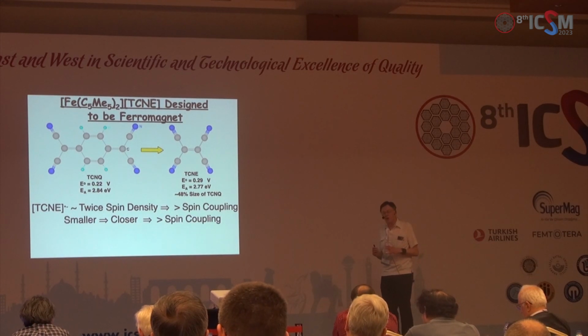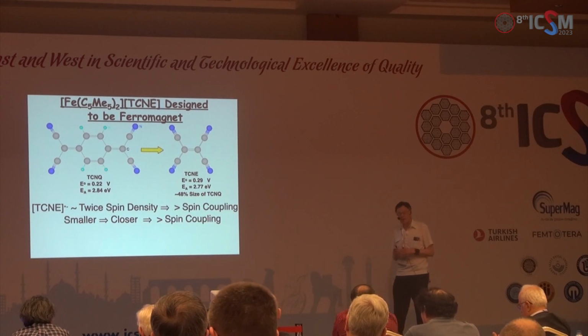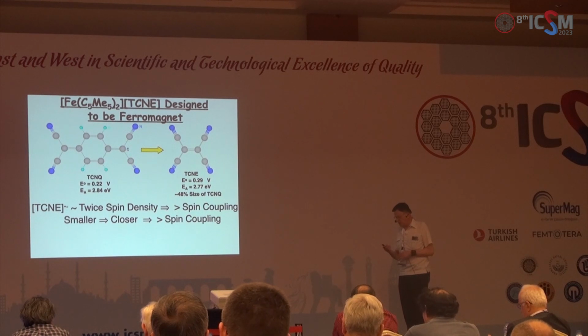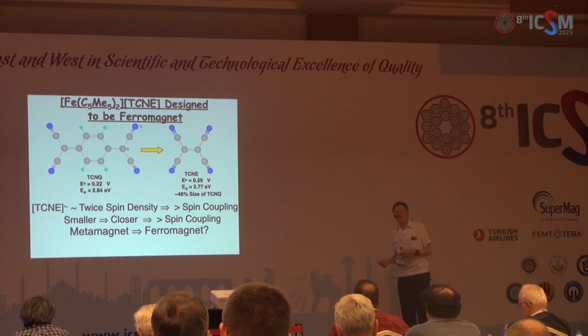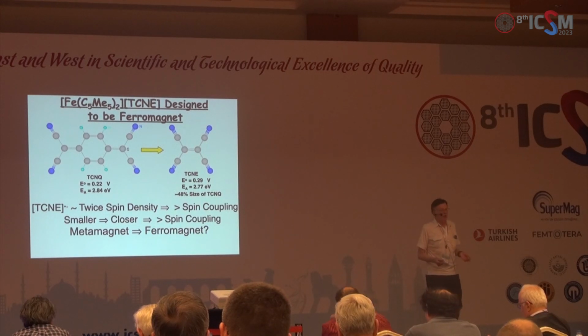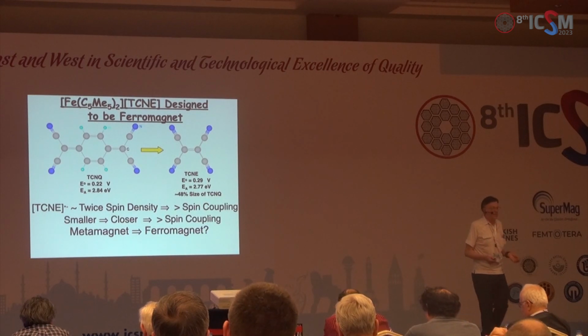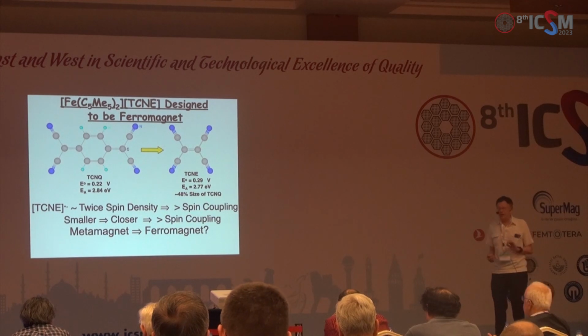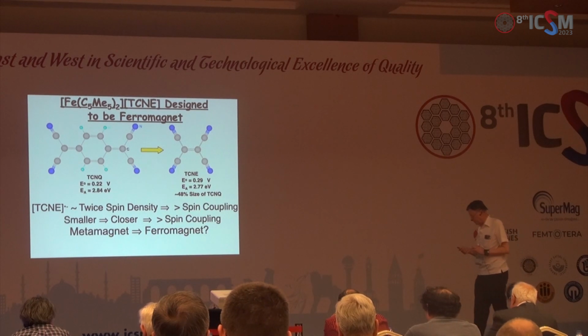It's also smaller, so it can get closer to something else and have stronger spin coupling. And so we anticipated and hoped this, in fact, would lead to a ferromagnetic ground state instead of an antiferromagnetic or metamagnetic ground state for this material.